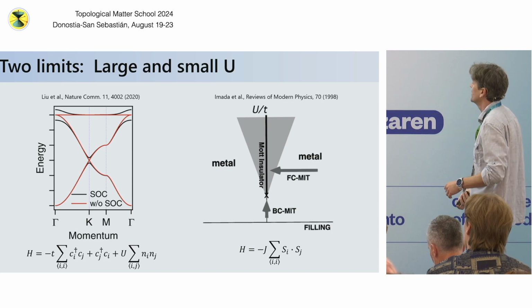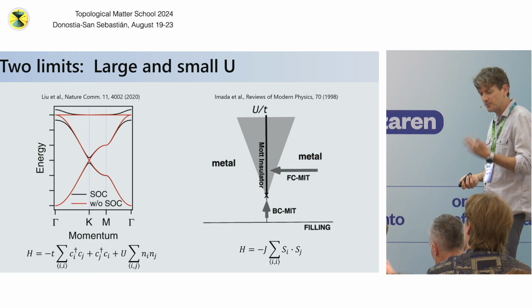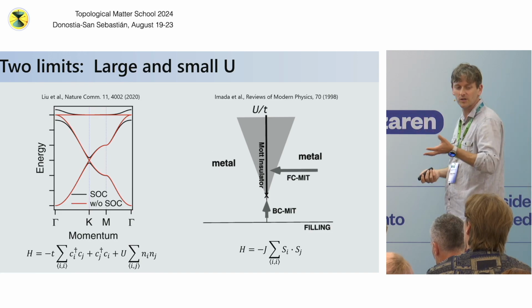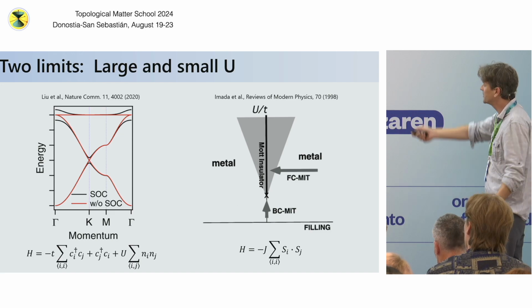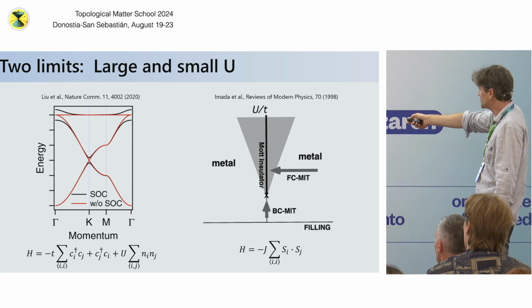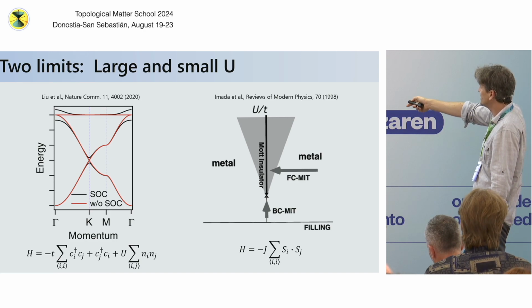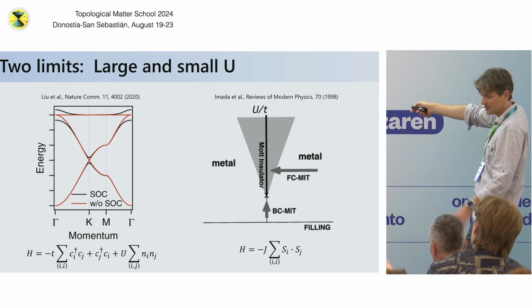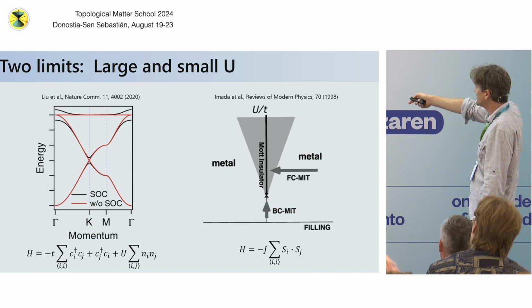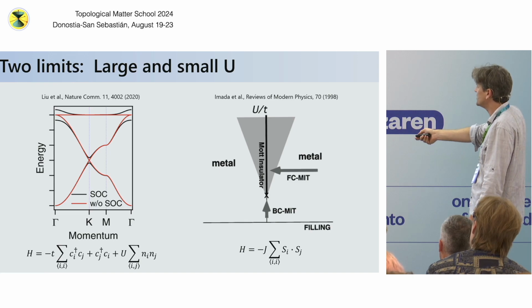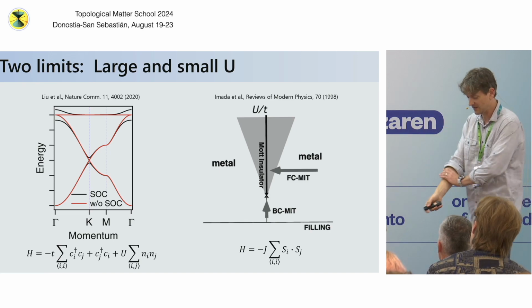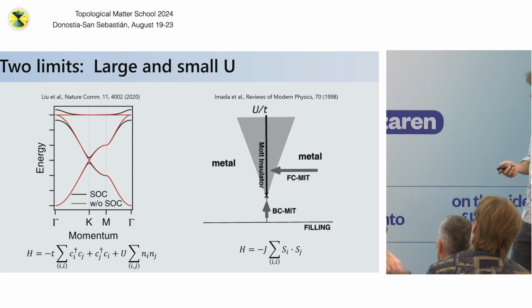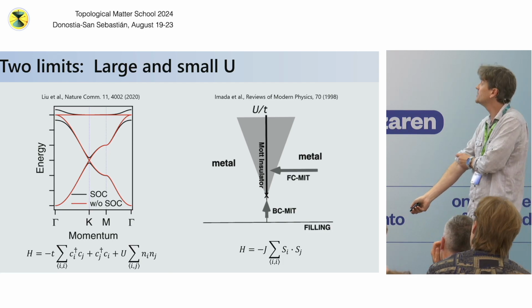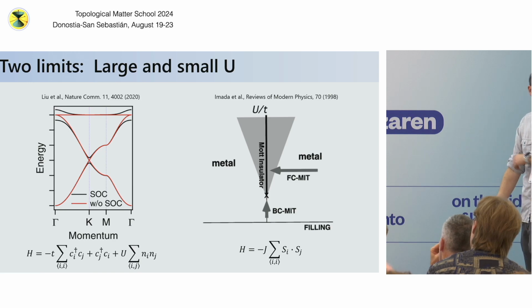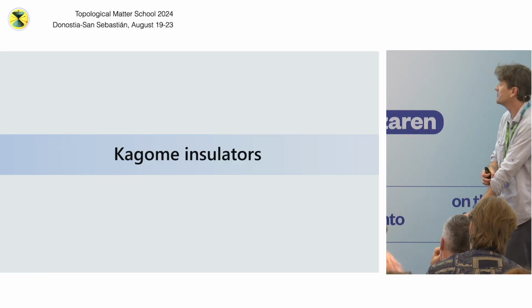And then the other limit, as we just heard in the previous lecture, is that if you push this system to half filling and then you start cranking up correlations, eventually you'll gap out the charge sector and you'll undergo this Mott metal insulator transition, right? So sitting at half filling and turning up correlations, eventually the charge degree of freedom gets gapped out. You have upper and lower Hubbard bands, and then this system becomes a Mott insulator. And since you've removed the charge degree of freedom, you can think about systems in terms of a Heisenberg model. We can think about exchange between electrons in the magnetic sector, okay? And so these are the two limits in which a lot of the more interesting phenomenology of Kagome lattices have been discussed. Okay, so first I want to start off with Kagome lattice insulators, okay?